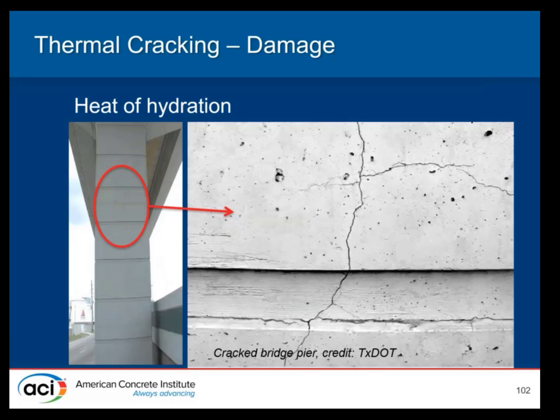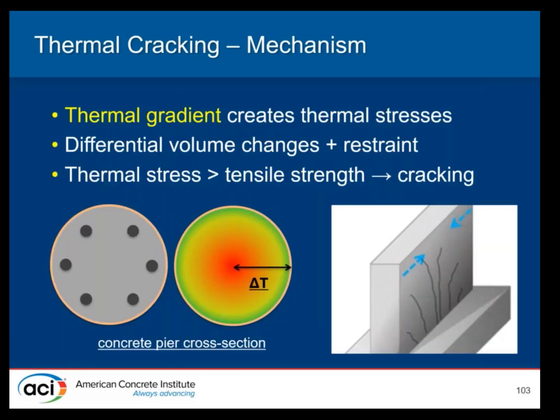When the surface cools rapidly to ambient temperatures, there's a huge difference in temperature, and the subsurface contraction due to cooling is restrained by the hotter interior concrete that doesn't contract as rapidly. And that restraint causes tensile stresses that can crack the surface concrete as a result of this uncontrolled temperature difference across the section. In most cases, thermal cracking occurs when concrete surfaces are exposed to extreme temperature rapidly. The concrete members will expand and contract when exposed to hot and cold ambient temperatures, respectively. Cracking occurs if this bulk volume change from temperature variations is restrained. This is sometimes called temperature cracking, and is a later age, longer-term issue. So basically what's happening is we have a concrete member in a big delta T, and we have thermal stress as a result of that difference in temperature, where the core is staying hot and the exterior is cooling, and that difference in the thermal stress leads to tensile cracking when the tensile strength is achieved.